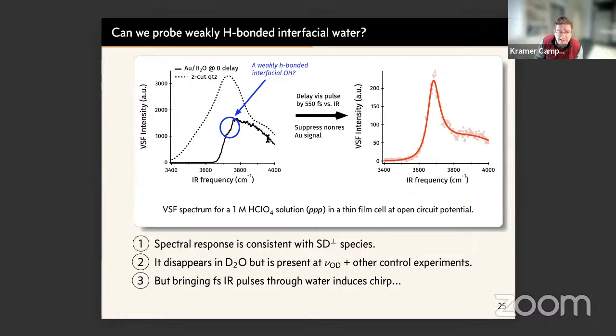In contrast, when you get up here to say 3,800 and 4,000 wave numbers, they're basically all getting through and generating sum frequency off of the metal. And this is, of course, to be expected. The bulk water OH stretch is peaked at, say, about 3,300 wave numbers and decreases as you get down to about 3600. But if you squint very carefully at this, you would say, well, if I really look here, it looks like there is something, right? There's maybe a little wiggle in this line. And perhaps this is a spectral feature.